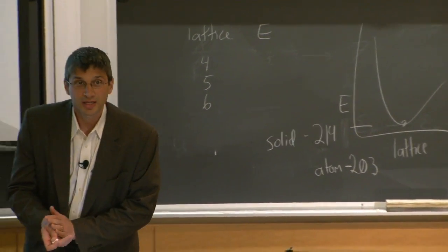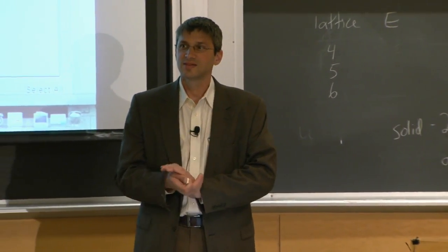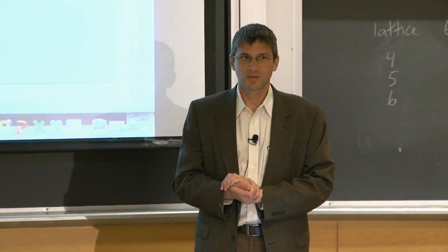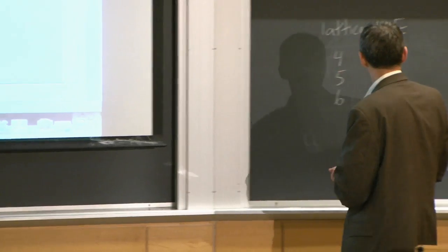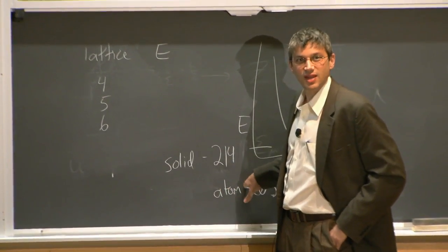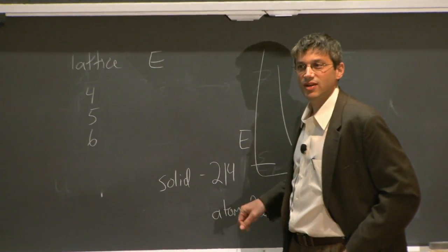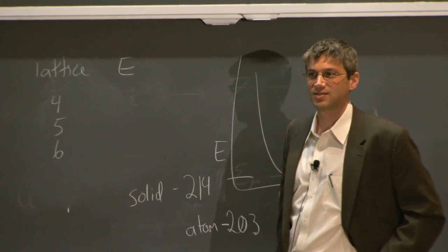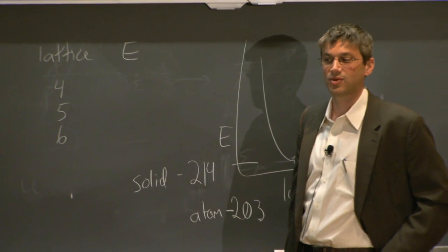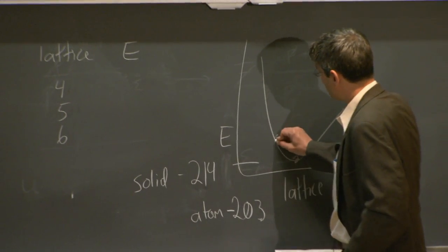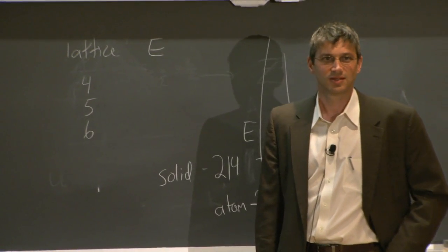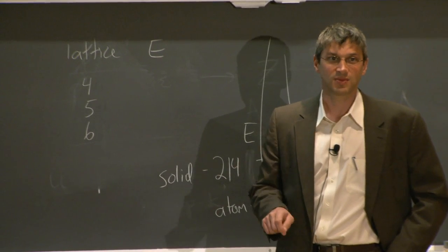And then I look it up, and I actually see that it's 4.6, because it's been measured in experiments. What did I do wrong? The cohesive energy of silicon, from my calculations, I did the solid minus the atom, and I find it's 11 eV. Are you sure you're in the right lattice constant for the solid? Maybe not. Maybe I was here. But I was 6 eV off. It's a really good point. That's one thing to check. What else?